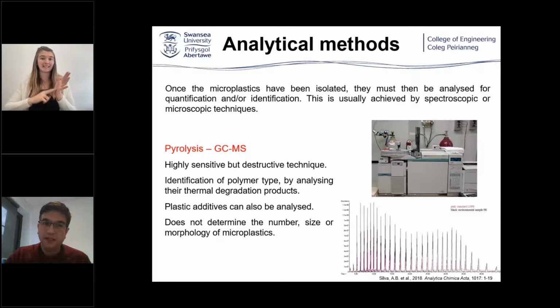It has been reported recently the use of pyrolysis GC time of flight mass spectrometry for the analysis of nanoplastics. It will allow you to identify the polymer type, and it could also give you information on the additives in the plastics. But because it's a destructive technique, you won't be able to know the number or the size or the morphology of your material.